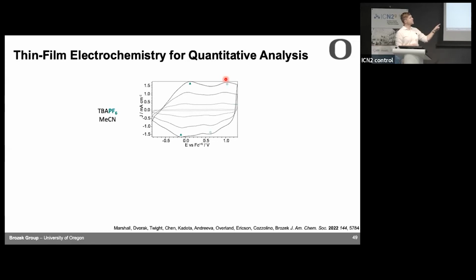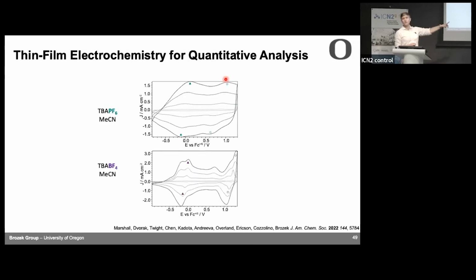So we repeated this measurement, but with BF4. So we moved to a smaller anion and everything changes. There's more redox waves, they're sharper. Depending on how you assign them, they've moved to less positive potential. So everything gets easier. So this was consistent with this idea that the redox chemistry of a MOF is really governed by how easily you can compensate those charges.